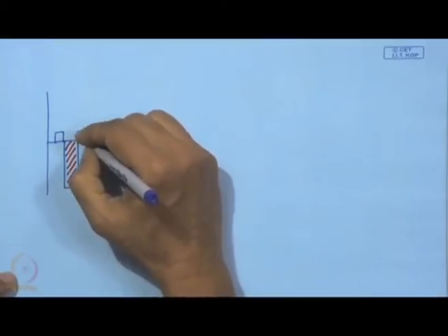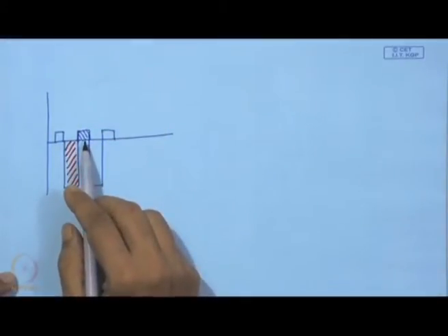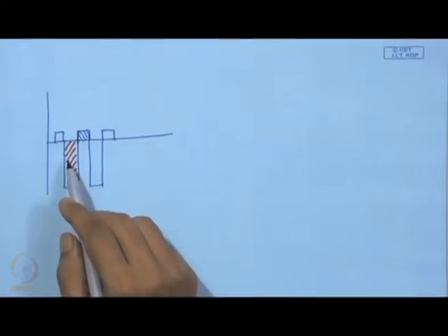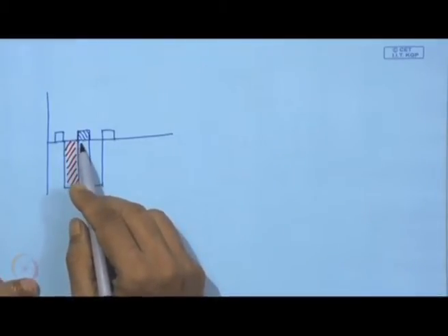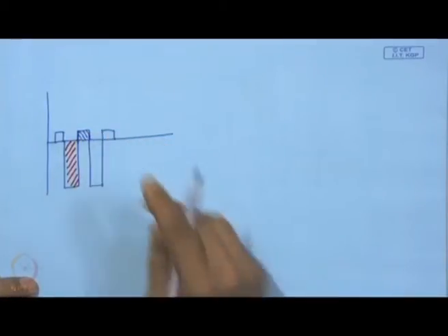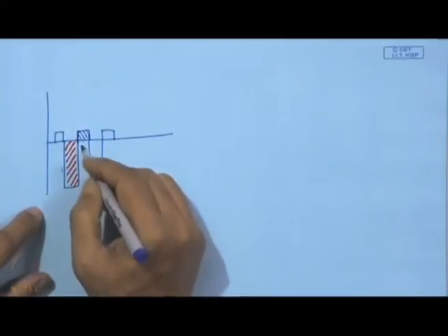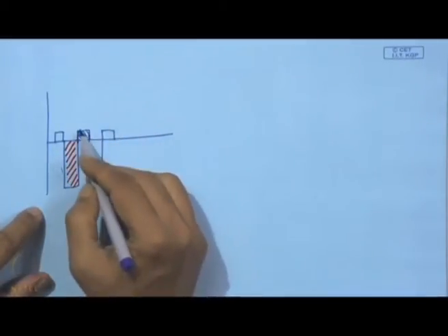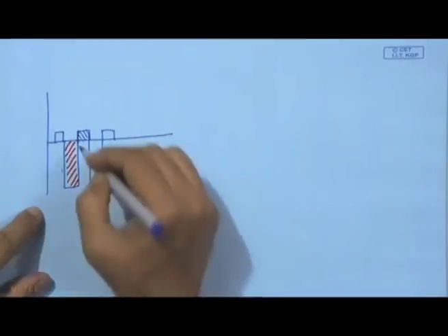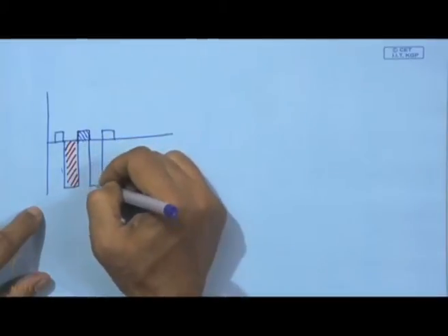This positive polarization is there because there will be accumulation of charge and that has to be neutralized, and to ensure that the whole thing is neutralized here, we have to have a little bit of positive biasing to ensure that all accumulated charge during this period is totally discharged and it is at the 0 level, and the process of activation of the cathode can again start.